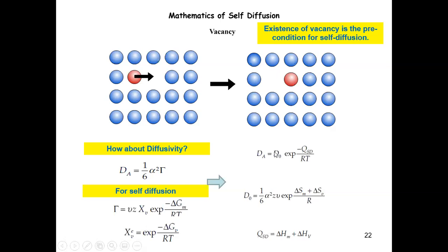You can write this as a temperature independent constant, and then you have this Boltzmann factor, and within this Boltzmann factor, you have this effective activation energy, which only takes into account a temperature dependent enthalpy term. And here you have the thermal fluctuations. And for the independent part, you have this term, which is also very similar, but you have to add the change of entropy due to the creation of the vacancy here. Okay, so that's basically the substitutional diffusion.